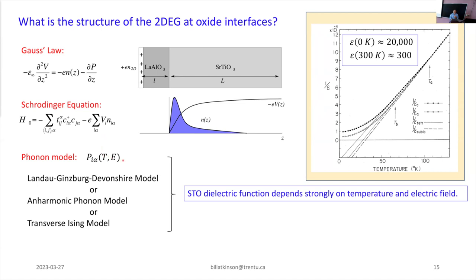Okay. And then I need some kind of a phonon model that gives me the polarization as a function of temperature and electric field. And we have used many different models. Qualitatively, they're all similar. Quantitatively, it's really a question of which one is best suited for the problem we're working on at the moment. So for this particular project, we use this quantum anharmonic phonon model. I'll show you more about this on the next page. What I wanted to emphasize here is that we're solving three coupled equations self-consistently, because to get the potential and electric field, you have to solve Gauss's law, but that depends on knowing the electron density and the polarization. So everything depends on everything else. Solving these equations self-consistently is hard. And my students spend a lot of time getting their code to converge. This is the rate determining step in these calculations, is getting convergence. It's really, really hard.